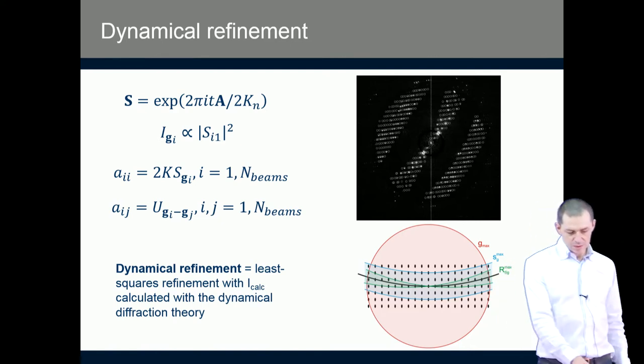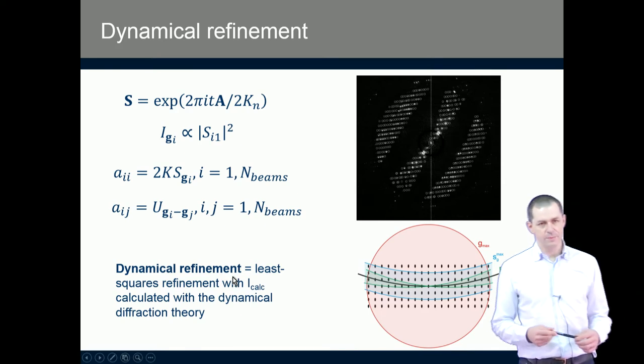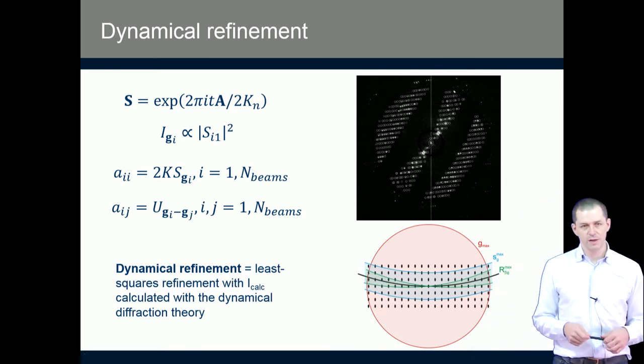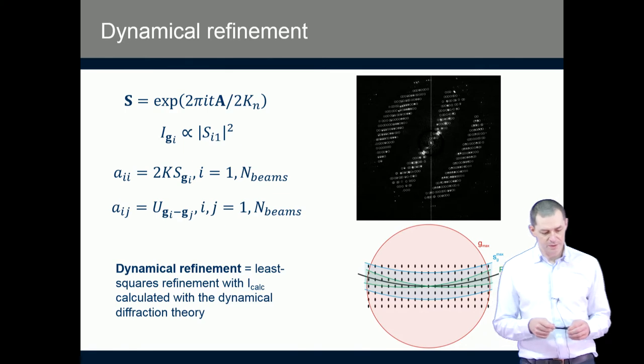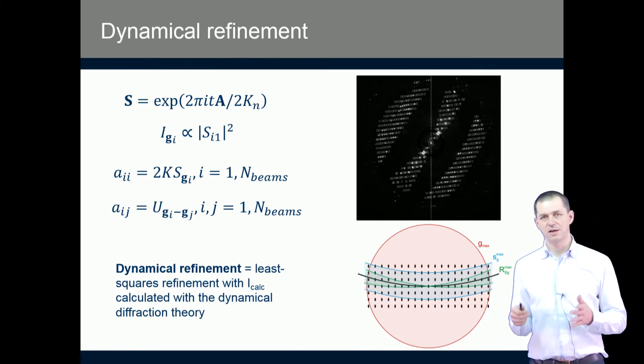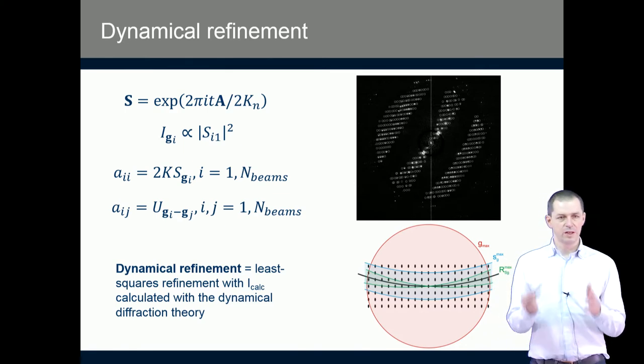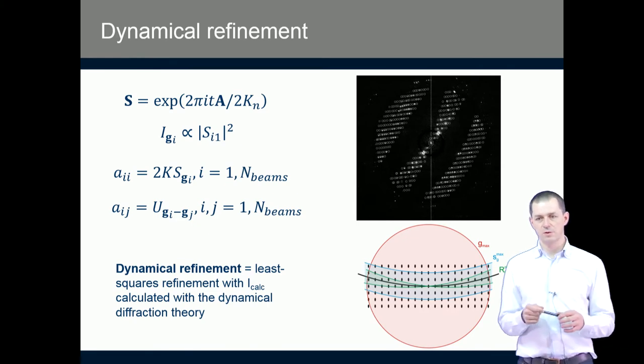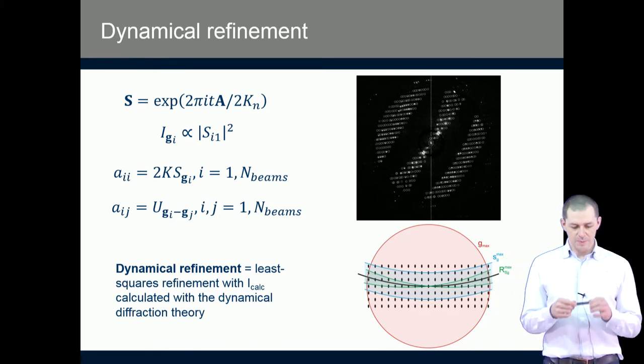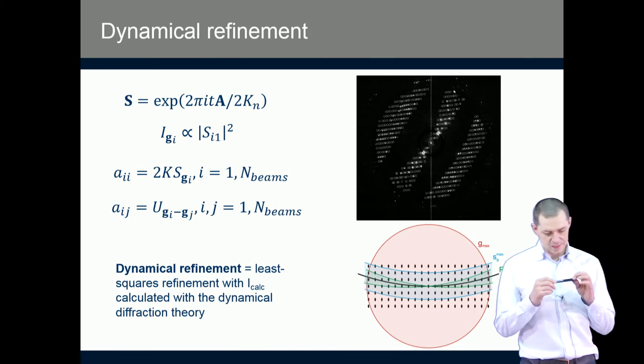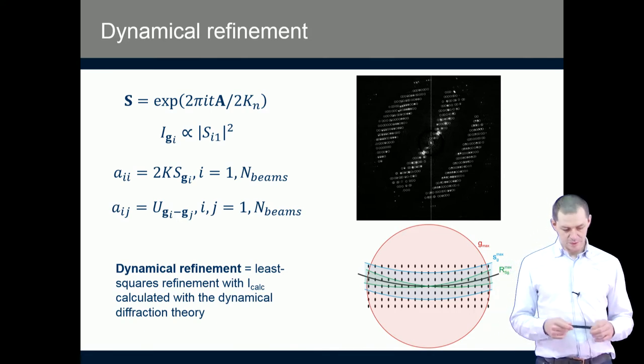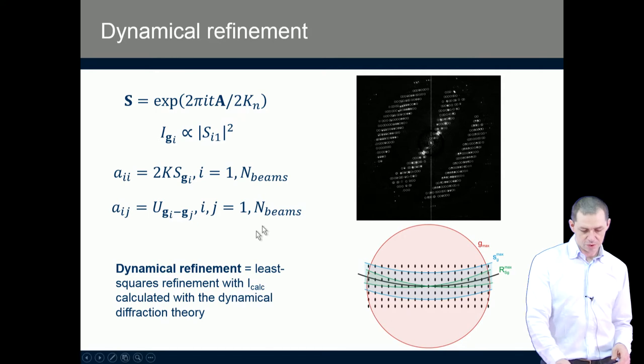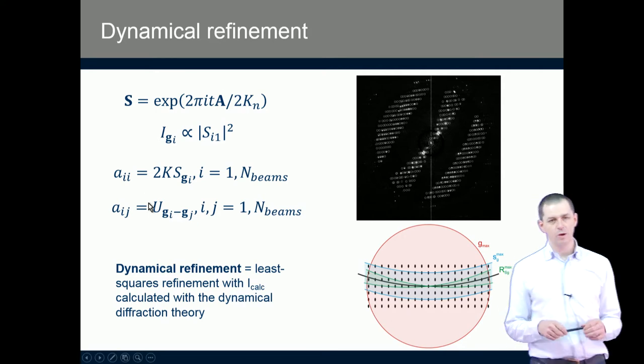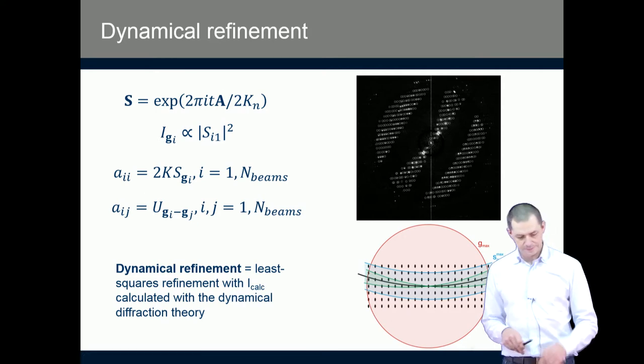So when I use the term dynamical refinement, that is a least squares structure refinement where the calculated intensities are obtained not with the kinematical approximation as squares of the structure factor amplitudes, but they are obtained using the calculation involving dynamical diffraction theory, so essentially these formulas, and they include the dynamical effects.